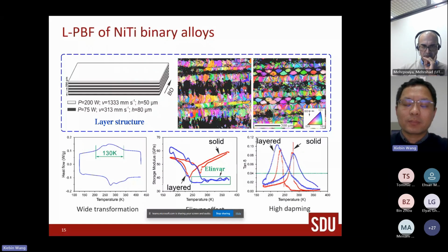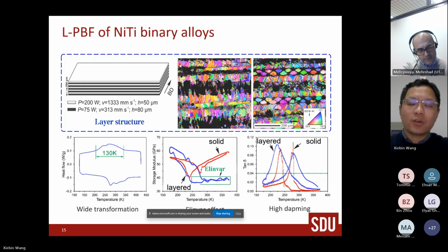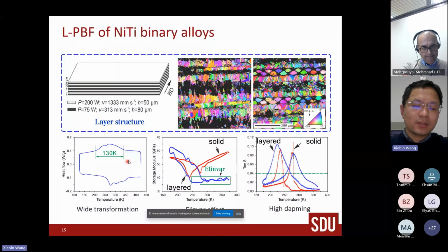the black layer is martensite phase, because martensite has very fine laths, and for EBSD it's not possible to get clear Kikuchi patterns. Then at room temperature, we got an austenite and martensite layered microstructure. And for these materials, we could widen the transformation interval.